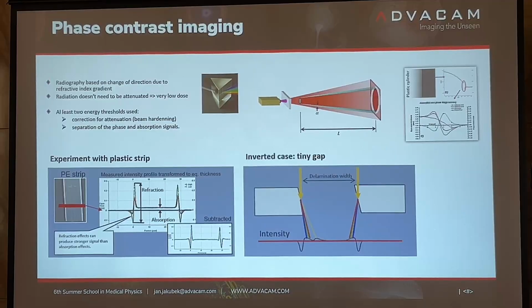This image shows it. This is a thin polyethylene strip, and you see this kind of enhancement of edges, dark and white, dark and white. With one energy, this is shown in green here. The signal is bigger. With another energy, the signal is less, because the angle is different. But the attenuation is the same. So here it is recalculated to equivalent thickness to have it the same.